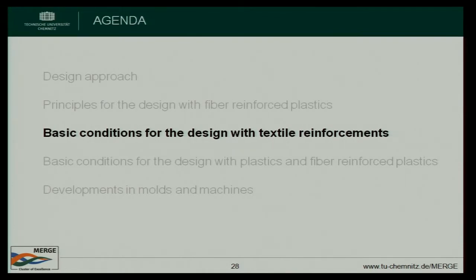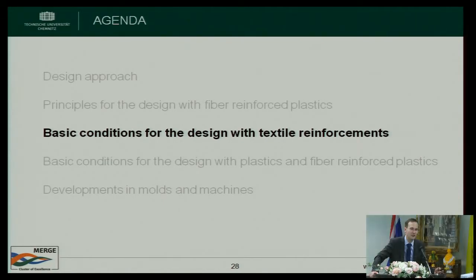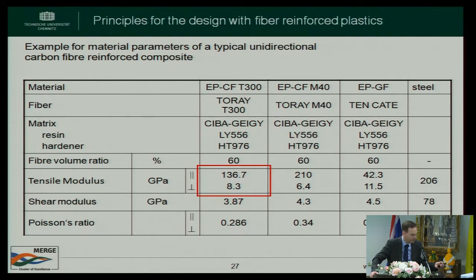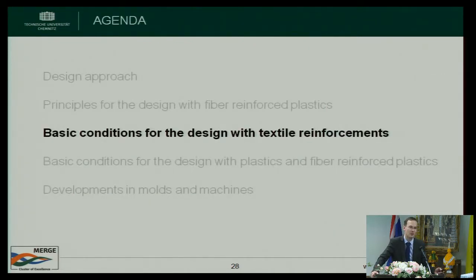So now, a single fiber is quite nice to have, but with a single fiber you cannot make any part. First you have some boundary conditions. Let's say we have the part that I showed before, and we want to integrate some reinforcements inside. You cannot take a single fiber, as a single fiber has a diameter of, let's say, 14 micrometers. You cannot handle a single fiber. You always have to make some textile fabric from the fibers.